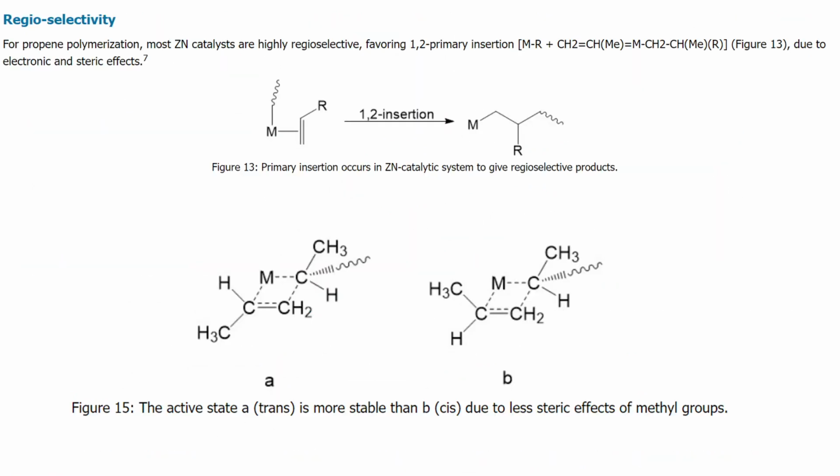So that's the way to explain because when you have this kind of transition state, you can see after polymerization the two methyls, their orientation would be in the same state. So they are actually above or below, but the point is they are similar to each other. And here you can expect to have this kind of sigma plane. So they are actually meso compounds, or meso diads is what it is called actually. Meso diads can be formed, and it's the transition state for that.